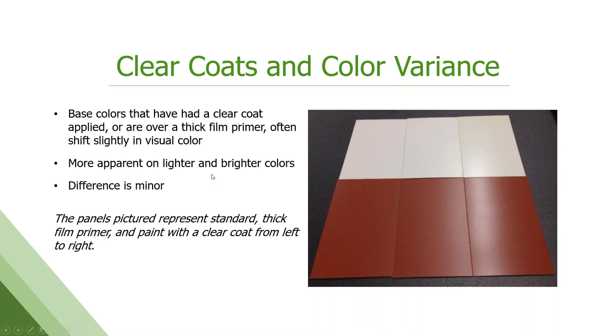So if you're going to use a clear coat over a darker color, you might visually see the difference. And you can see here the white on the top. The panel on the left is just standard primer and top coat. The one in the middle has a thick film primer added. And then the one on the right is thick film primer, color coat, and clear coat. And you can see in the lighter colors that it has shifted a little yellow. But in the darker colors, you really can't tell.